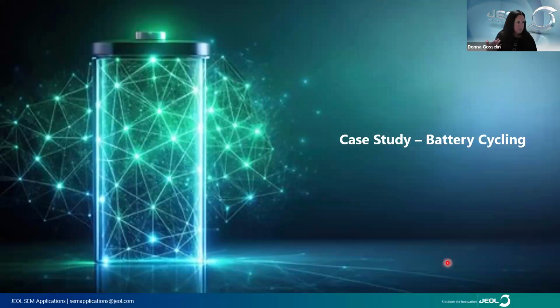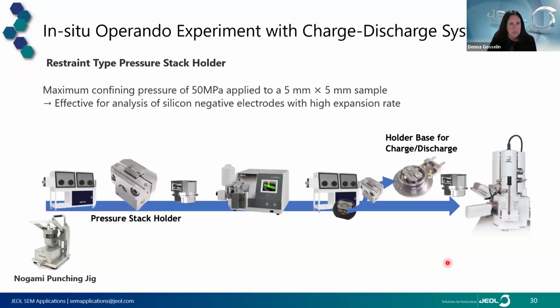So my last example in the next few slides is going to be a battery cycling experiment within an SEM. And in order to perform this in situ charge-discharge experiment, we designed a very unique pressure stack holder. And this was designed specifically for a solid state lithium-ion battery, where we're looking at the silicon negative electrodes specifically. They have very high expansion rates, and this pressure stack holder allows us to cross-section and observe the material while maintaining a confining pressure.